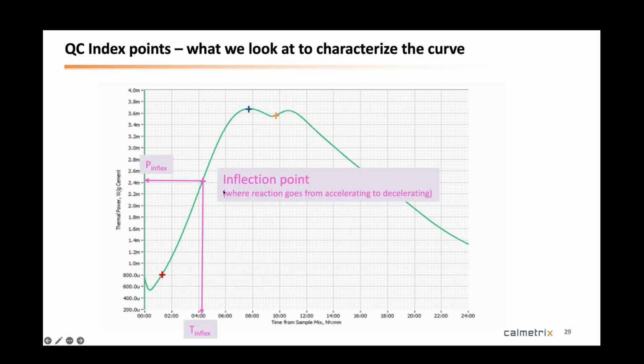The inflection point is also interesting because in this curve, since it's the speed of reaction, it actually shows you where the reaction goes from accelerating, where it goes faster and faster and faster, to decelerating. So it's also indicative of where the final set is about to occur. Not exactly the final set, but again, it's a very convenient point on the curve to look at to understand how this evolves in terms of consistency.